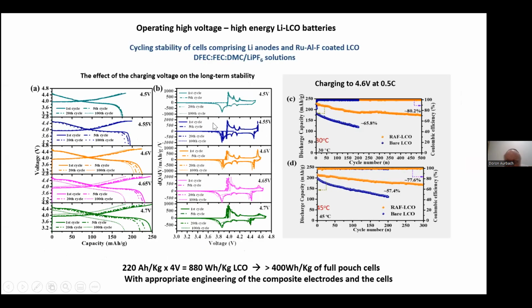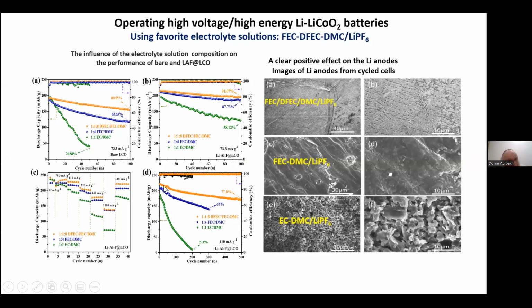the combination of good coating and the use of the right electrolyte solution, we see very nice stabilization, and the stabilization is both on the negative and the positive. So you can see here, we take lithium electrodes after cycling in such cells, and we compare the morphology of the lithium electrode through post-mortem analysis, and we see very clearly the very nice stabilization effect of the solution comprising the two fluorinated co-solvents, based on the surface chemistry and the understanding that I showed you before.